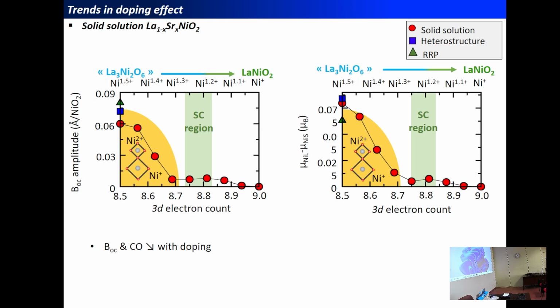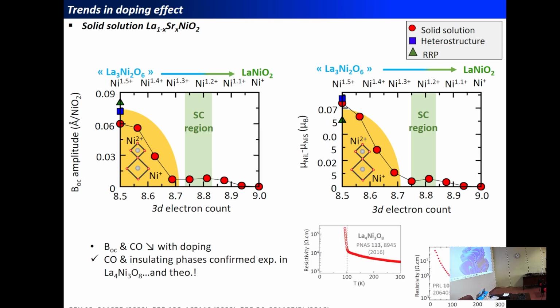And therefore, if we put more and more electrons on the nickel cation, we can track the breathing distortion amplitude versus the 3d electronic count, but also follow the nickel cation magnetic moment asymmetry as a function of the doping content. And what you see is that starting from the half-doped situation where we have the charge ordering, the breathing distortion progressively disappears, the magnetic moment asymmetry also disappears, and when it's nearly zero, it corresponds exactly to where the superconducting region appears experimentally. And therefore, it means that the superconducting region should be in the vicinity of a charge ordering if we start from the left side of the phase diagram instead of starting from this side of the phase diagram.